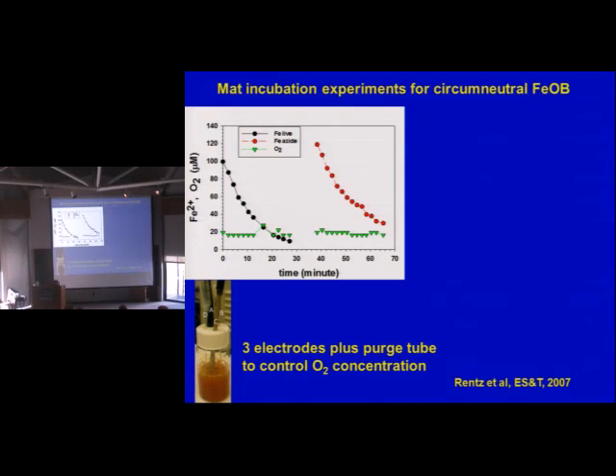So what Jeremy did was we actually redesigned a little vial. Always try to do things so you can do things out in the field. And in this case, we try to keep the oxygen about 20 micromolar. That's the green here. We have an experiment. We started out with iron live. So we put the mat right in, and you can see this decay curve. Beautiful pseudo first order look. We stopped the experiment, said, okay, add the azide, and we still got oxidation. All right? That should be only due to abiotic or inorganic chemical oxidation.